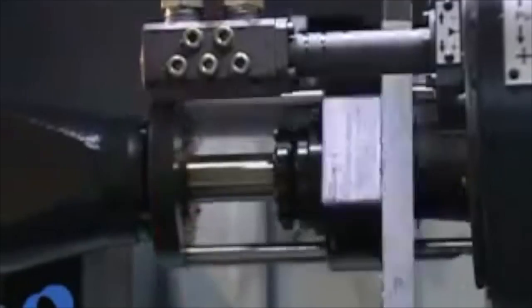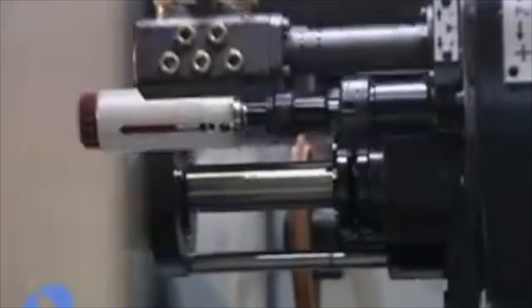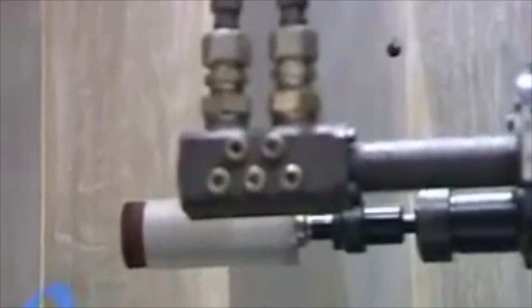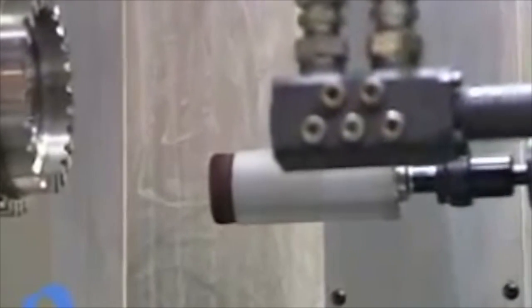About the grinding wheel. The grinding wheel is composed of abrasive particles and bonding material. The grinding wheel of Viper grinding is changing from cubic boron nitride super abrasive to aluminum oxide abrasive instead. The aluminum oxide abrasive has a soft ceramic bond that enables the tool to be cut freely, avoiding excessive overheating when grinding.